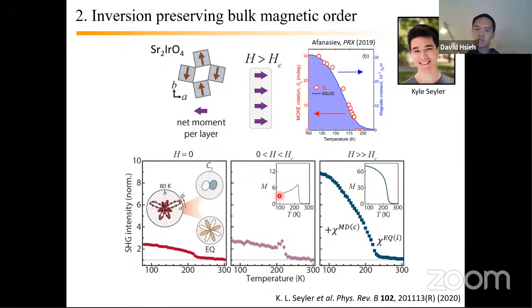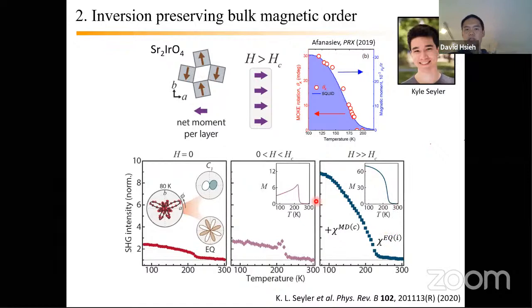So here I'm showing SQUID data. This is bulk magnetization versus temperature. You can see that this contribution now gets superimposed on the surface contribution, right? So you have this sort of order parameter-like upturn accompanied by this peak structure. And then as you go to much higher fields where your sample is fully magnetized, you get dominated by the bulk magnetic dipole term. And so you then perfectly mimic the bulk magnetization data. So all that is to say that these things do get entangled in your SHG response, and you have to take care to separate them out, but there are ways.